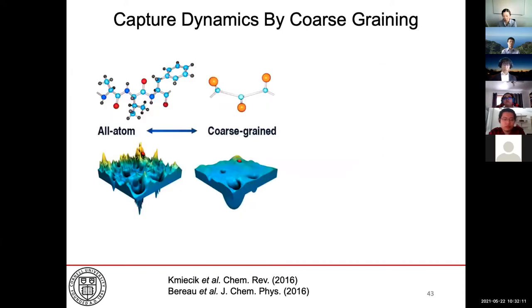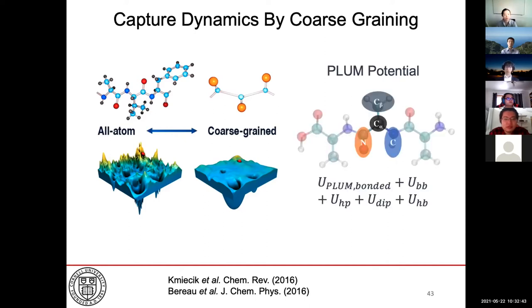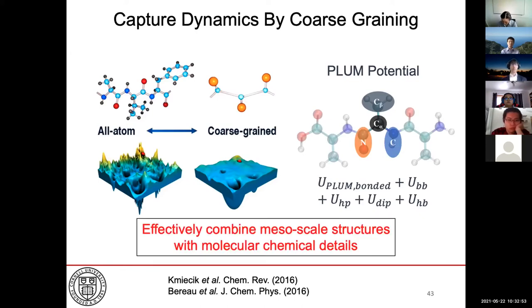And the approach that I took was coarse-graining. And coarse-graining is a reductionist approach where only the important structures or details that need to be captured are modeled. And this reduces the number of interactions to be computed, and it also smoothens the underlying energy surface for faster statistical sampling. And therefore, we actually get two birds with one stone. And what we need here is a coarse-grain model that can capture conformational changes in the protein backbone, meaning a model that can fold protein structures. And for this purpose, I chose to use a potential known as the PLUM potential, which incorporates both bonded and non-bonded interactions, such as hydrophobicity, dipole interactions, and hydrogen bonds. And therefore, we can effectively combine the mesoscale structures with molecular chemical details.